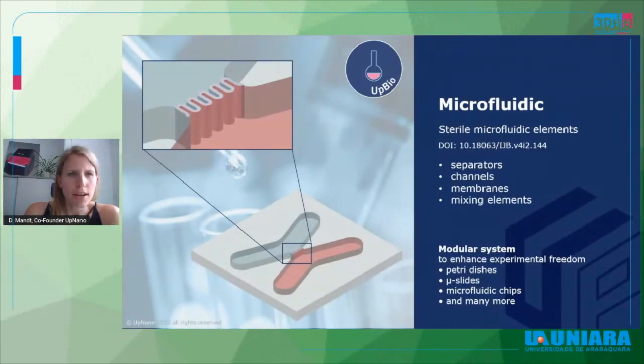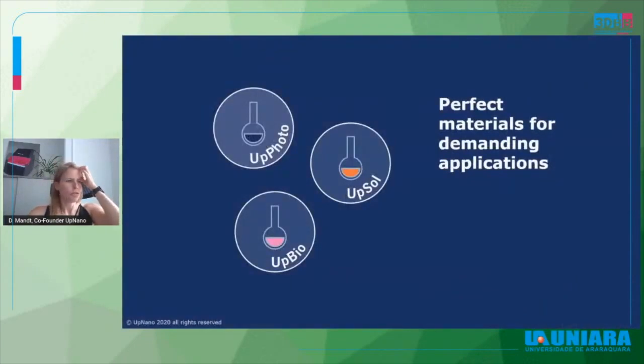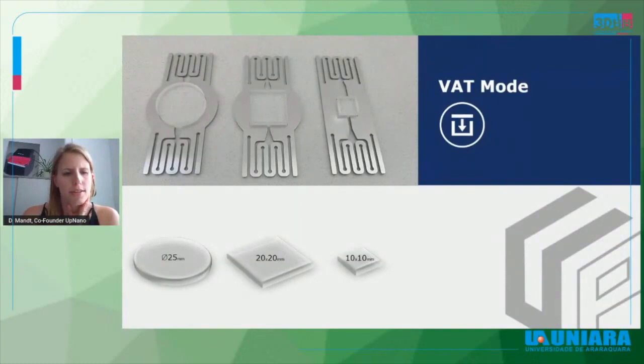When printing on the substrates I showed before, so on these glass substrates, there are different options. You can either pre-treat them with a silane solution to ensure that the parts stay bonded to the glass substrates, or, when they are very fragile and you would like to take them off these substrates again, this silanization process can be skipped. Then the adherence between the material and the glass substrates is not that strong, and the structures can be removed easily. This depends on the further use of the structures, and on what the final use would be.